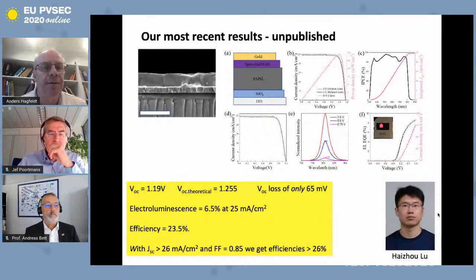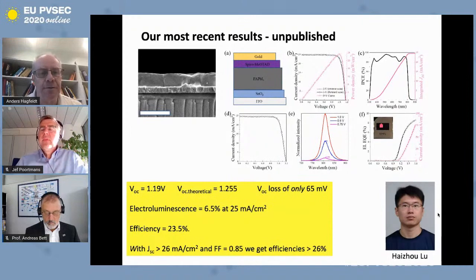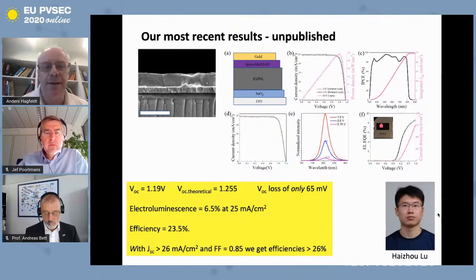What we are very happy with here is our voltages. We are at 1.19 volt at best for this band gap of 1.49. The theoretical highest possible is 1.255, so we lose only 65 millivolt, and we think that's a kind of record, I think, in terms of lowest VOC losses. That also corresponds to a very high electroluminescence, which we also think is at record levels of 6.5% at the short circuit current of the device. So this gives us an efficiency of 23.5.